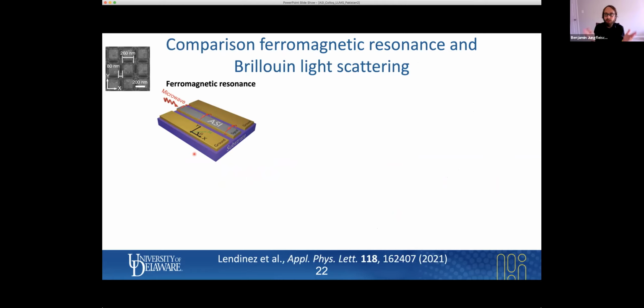So we have here a coplanar waveguide. This is a microwave antenna with two ground lines and a signal line. We pattern our spin ice directly on top of the signal line using electron beam lithography and deposition of 20 nanometers using electron beam evaporation, followed by a lift-off process. And this results in hundreds of thousands of elements on the signal line, which we expect to behave like an infinitely extended lattice. I'm showing here a scanning electron microscopy image with the dimensions. So you see it's rather small and the alignment is pretty good.